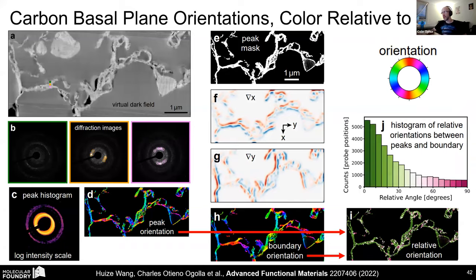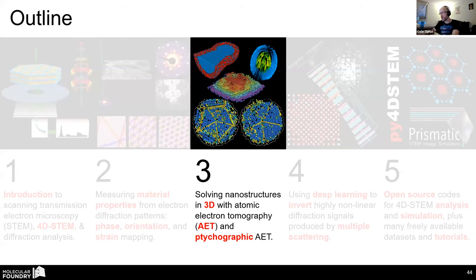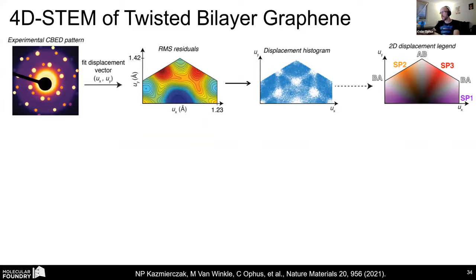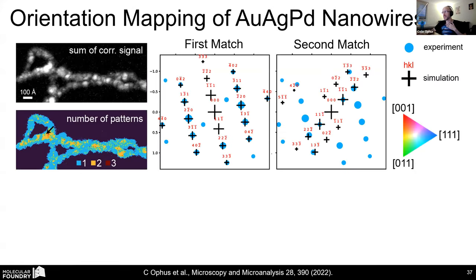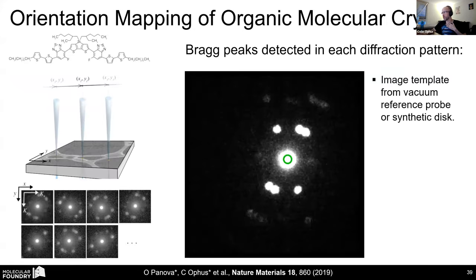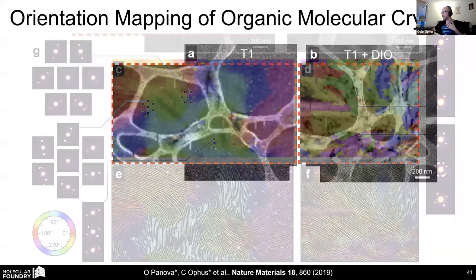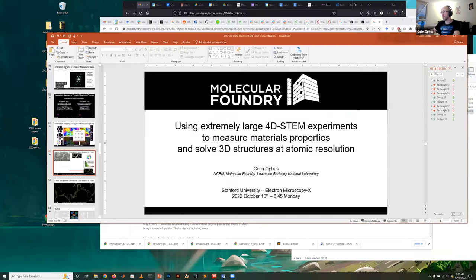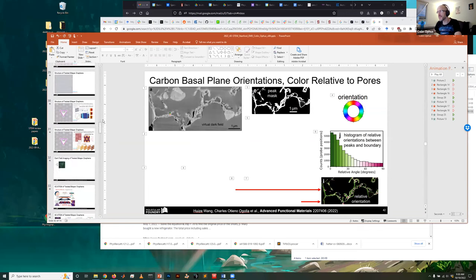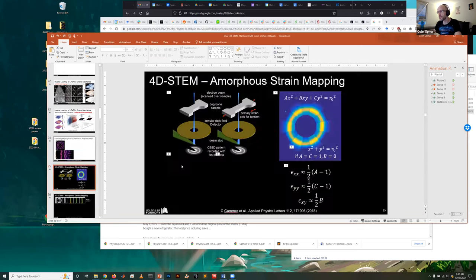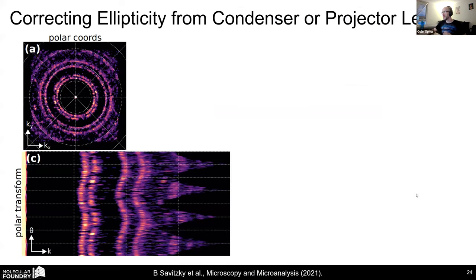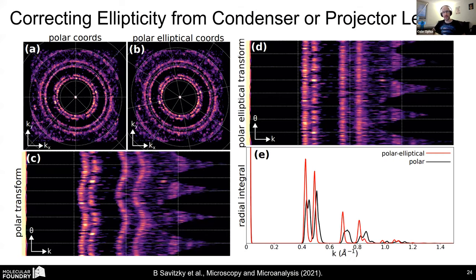So I don't actually have an RDF example here in this talk, but I can show you, in the elliptically corrected thing here. One of the reasons we do this elliptic correction, sorry, bear with me one moment because it will help to pull up the slide. Here we are. For the radial distribution function mapping, you take patterns pretty much just like this, although you usually want to use a very small semi-convergence angle so that you don't interfere with the probe.